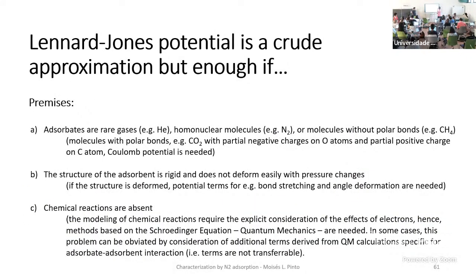So the Lennard-Jones is a crude approximation, because, as we introduced before, it was developed for rare gases, so it should work for rare gases interacting with each other. But it also works for the interaction of rare gases with adsorbates, because the interactions are also physical interactions, homonuclear molecules, or molecules without polar bonds like methane.